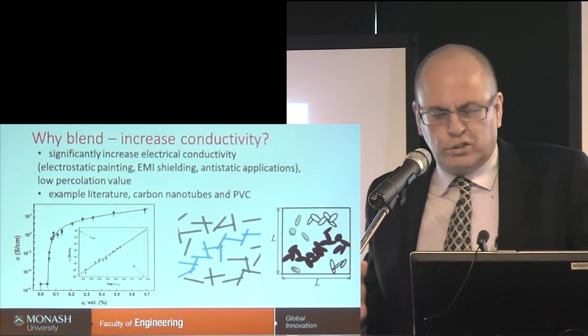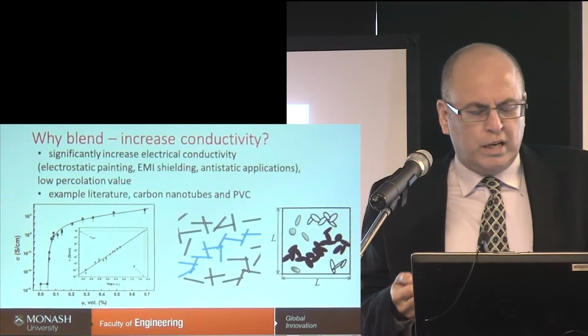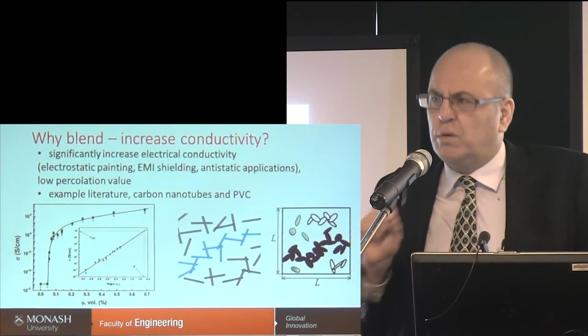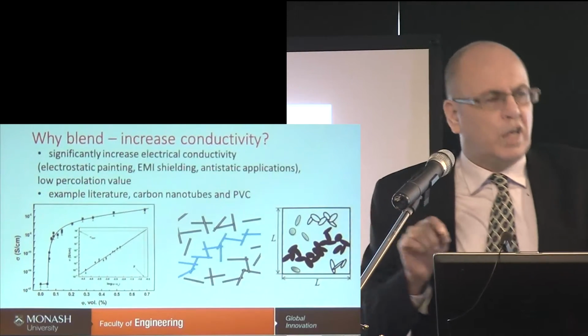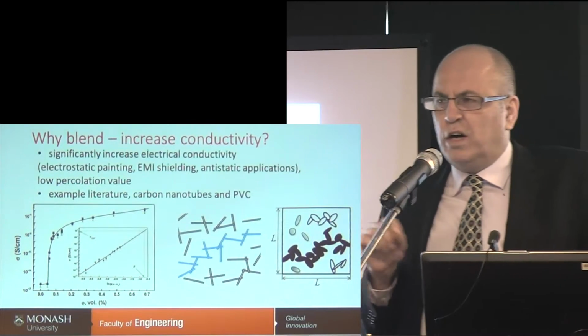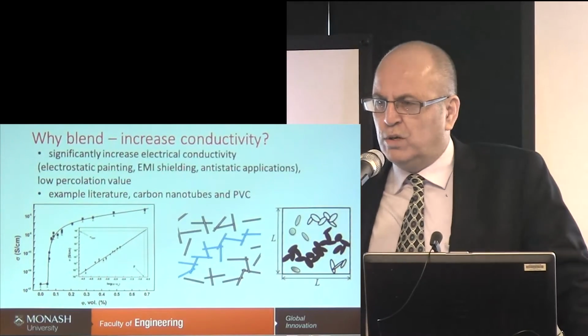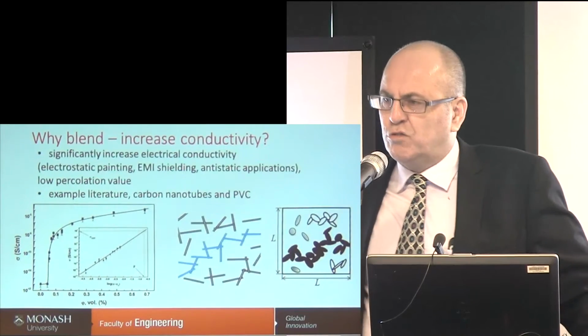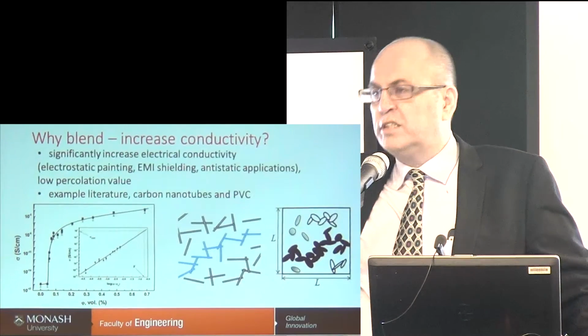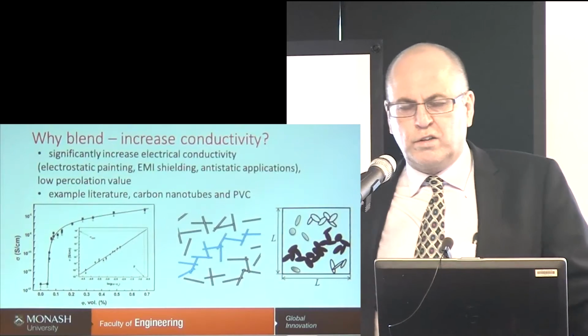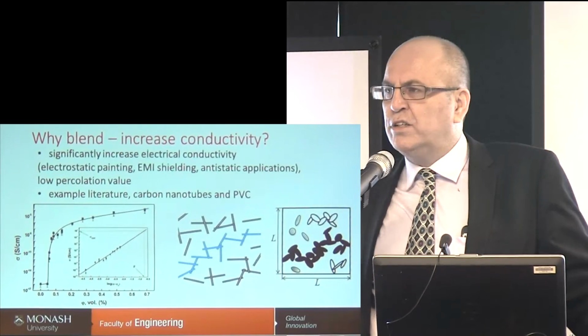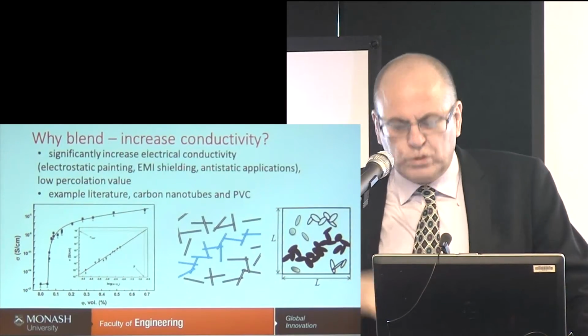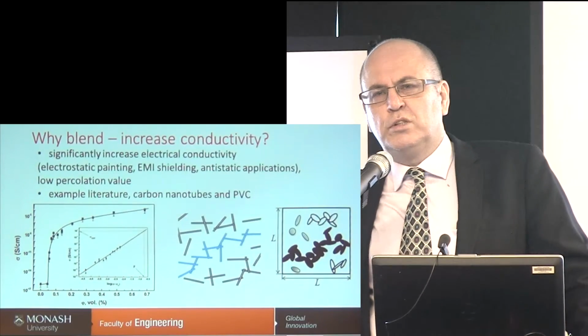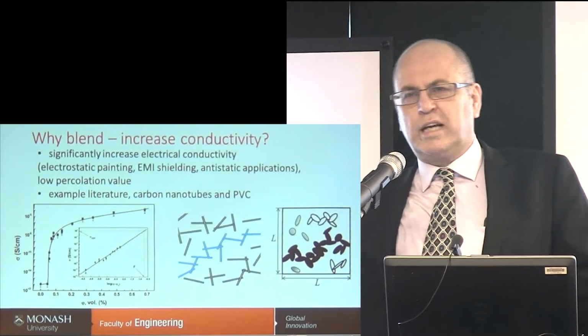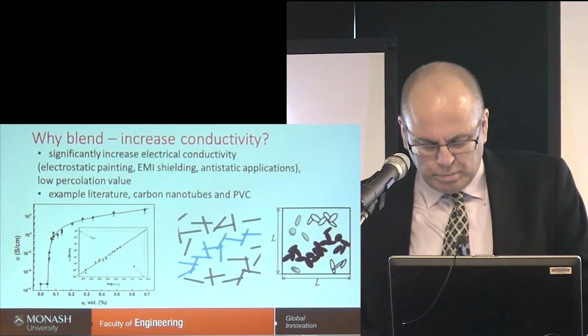Of course, conductivity is an important one. I just showed the example here of carbon nanotubes. This isn't our work. I just showed one with PVC, where you can see that very low amounts of a rod-like material, extended material, have a very low percolation threshold, the concentration you need to make it conductive. And on the far right, I've got some discs sort of representing a graphene or like material that would similarly have that high anisotropy. Whereas if you actually use spheres like carbon black or something like that, it's usually a much higher concentration required.